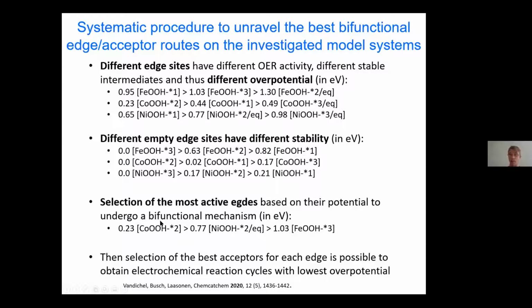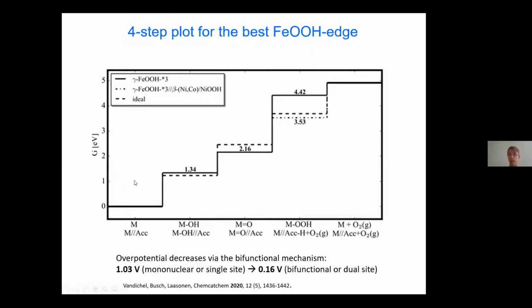But now that we have screened different edge sites and acceptor sites, so here I have just discussed the edge sites for gamma metal oxyhydroxides, we can have a look at what happens if we combine the edge site with a suitable acceptor site within the bifunctional mechanism. This is, for example, done for iron oxyhydroxide. If we combine that with an acceptor site that contains both nickel and cobalt, we can lower the overpotential from 1 volt to 0.16 volts for the trimetallic system.